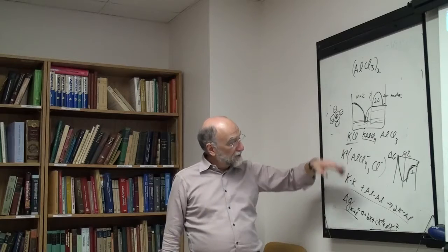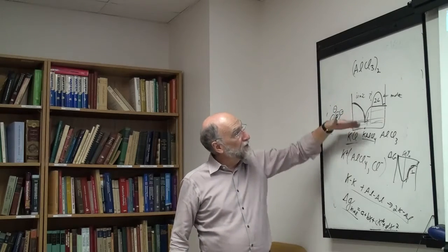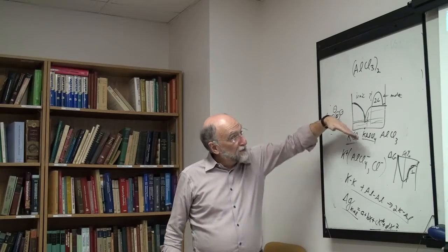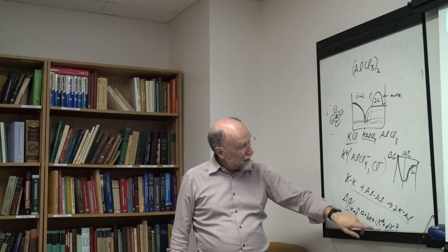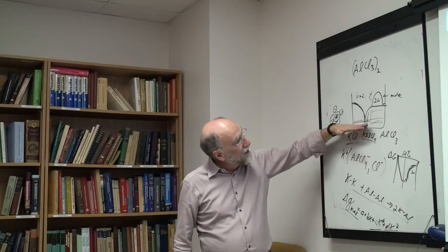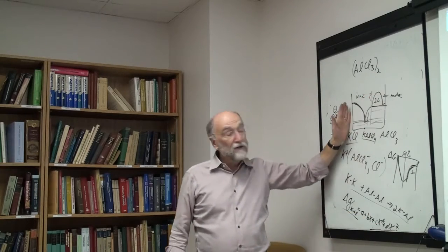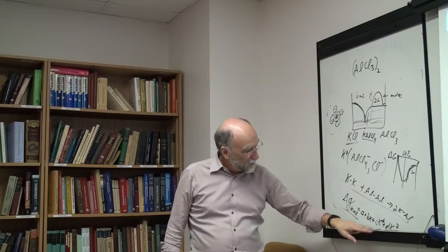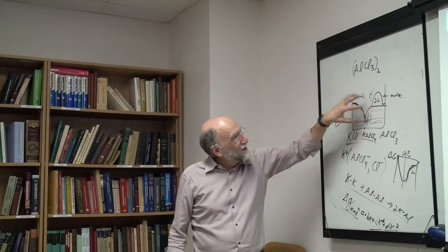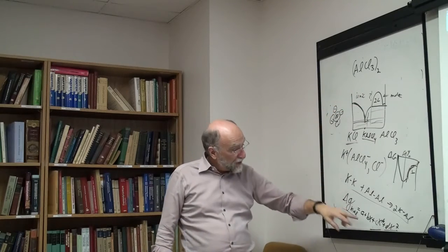The Redlich-Kister power series is x1 minus x2 to the n. As I said, it has the advantage of being always 0 at 50%, so it becomes kind of equal on both sides. Whereas normally if you use a power series, a term like x to the 6 is only important on this side. It doesn't have any effect over on that side. In this particular case, that's what you want. You want terms that only affect this side, that don't affect the other side. If you use a Redlich-Kister x to the 6th term, it affects both sides. You don't want to do that.